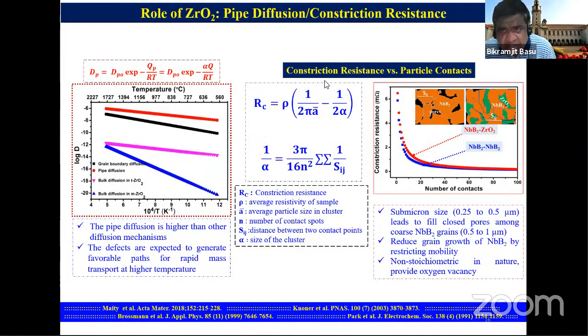So in spark plasma sintering, there is something called constriction resistance. When the current passes through the different particle boundaries, it experiences certain resistance, and this resistance can be theoretically calculated by this kind of expression, where RC is the constriction resistance, rho is the average resistivity of the sample, a is essentially the average particle size in the cluster, and alpha is the size of the cluster. Now, we have done these simple calculations to find out how this constriction resistance is reduced with more contacts in this particular niobium boride zirconia system.